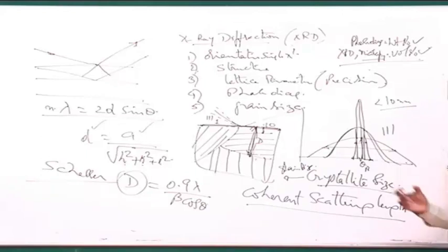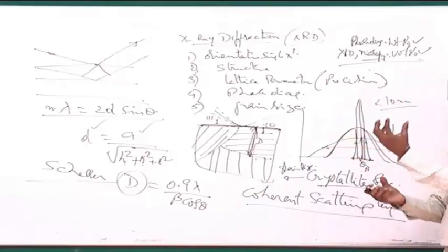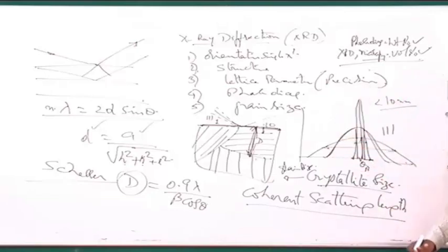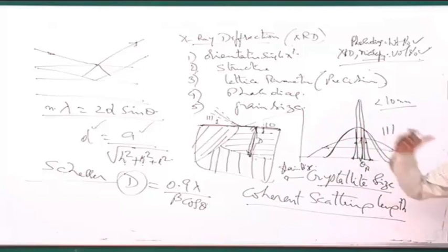You can also get particle sizes by other methods. For example, you can do laser scattering, using what people usually call particle size analyzers. You can take particles, suspend them in a liquid, and allow a laser beam to fall on them, and by the way the beam gets scattered by the particles, you will be able to find out the particle size. So those are all particle sizes. Even SEM will give you particle size. SEM will not give you a grain size.